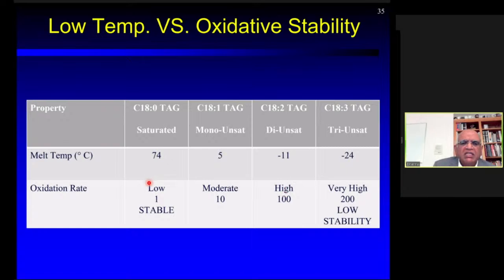So what I'm saying is, if we want to make a good lubricant, we should have the flow properties of a trilinolenin, but have the oxidative stability like a tristearin. That is what we have to achieve. To understand this well, nature has solved this problem already. As you can see here, it introduced a double bond, a kink, a cis double bond in the middle of the chain of a tristearin to make the triolein. Thereby, it dropped the melting temperature by about 70 degrees going from tristearin to triolein, as you can see.